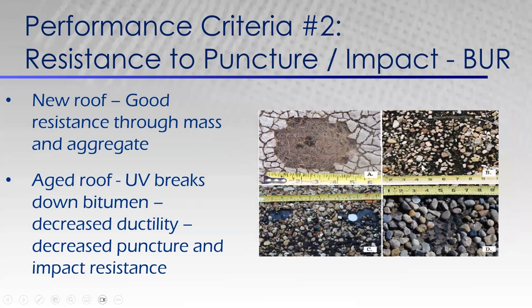And this is actually your plies that are now exposed in the roof. And over time, those microfractures will get larger and eventually, due to normal thermal stresses and expansion and contraction of the building, you're going to have the start of a leak through your modified bitumen. They're difficult to locate. If they're not as blatant as what you see here, they can be difficult to locate on site. So while the thickness of the system helps you with impact resistance, there is no real impact of thickness on puncture resistance on the roof through a built-up system.